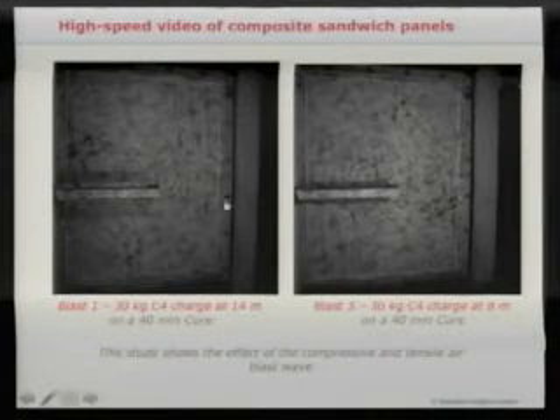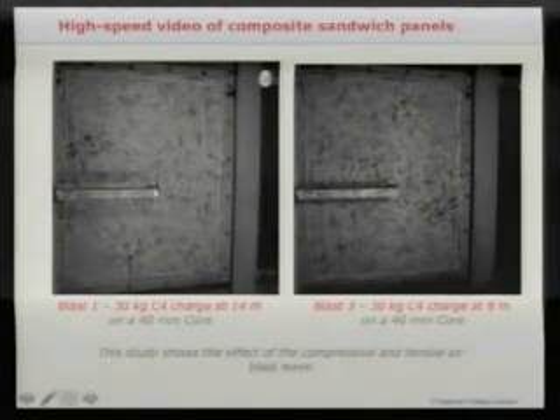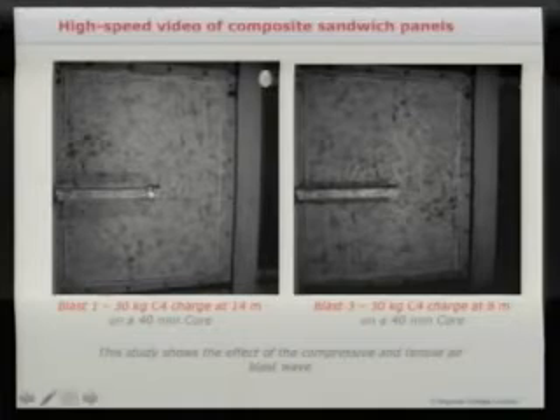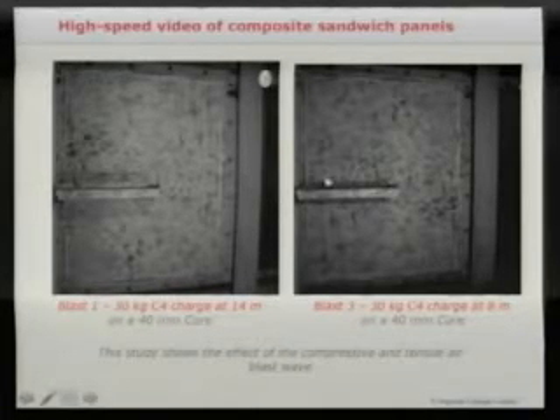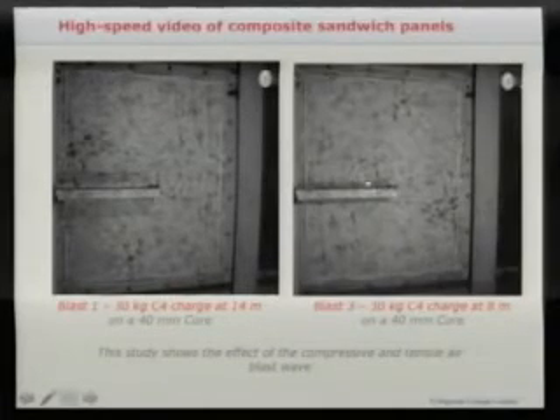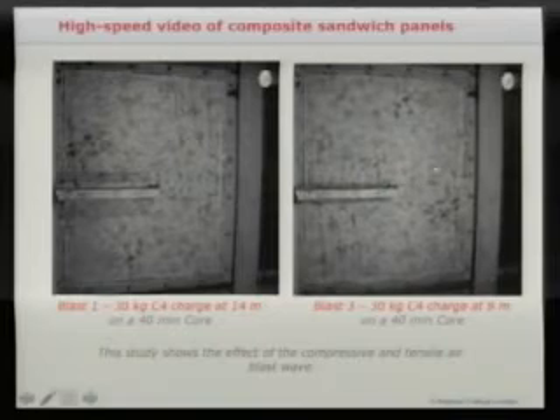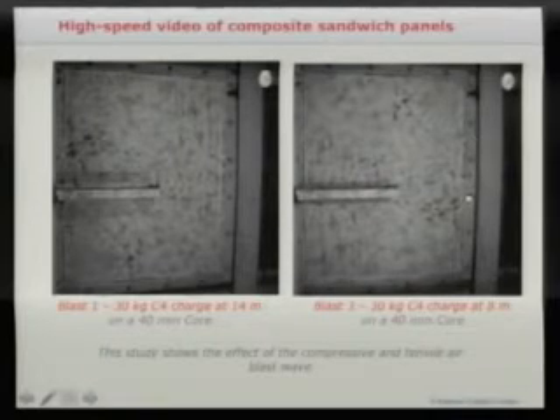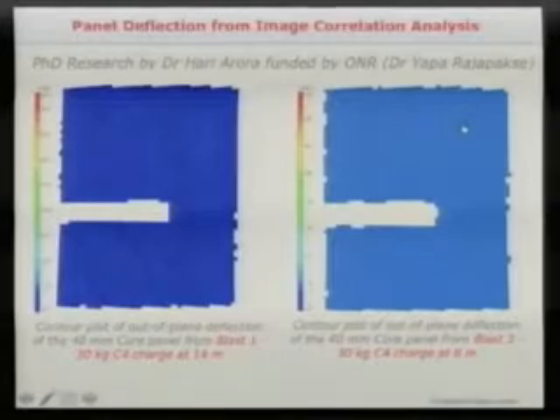So we do this at a series of different standoffs. This shows the charge at 14 meters. This is the worst case when the charge is closest at 8 meters. And if I play these, you can see the deformation here goes up to about 60 millimeters. This one, it goes up to about 130 millimeters. And if you look at that right-hand edge, it is moving slightly. That's because it's not as rigid as the corner.